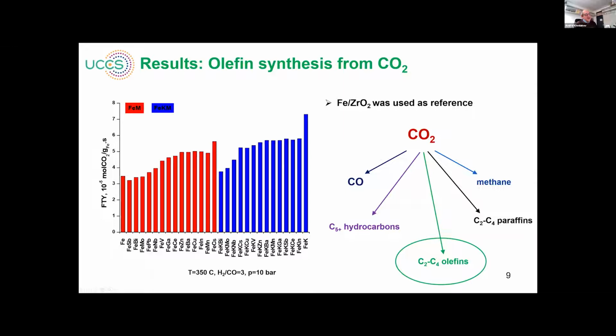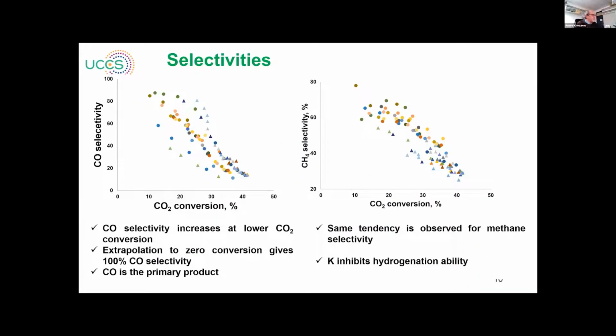When we conducted this reaction, CO2 was converted to CO, light olefins, methane, light paraffins, and C5+ hydrocarbons, I mean long chain hydrocarbons, typically C5 to C10 carbon atoms. On the next slide, I show the results we obtained for these different catalysts. First, the selectivity trend. We obtained a lot of experimental data. You see here CO selectivity as a function of CO2 conversion. The CO selectivity decreases as a function of conversion, and if we extrapolate the selectivity to 0 conversion, we reach about 100%. This suggests that CO, as we already said in the introduction, is the primary product of this reaction.